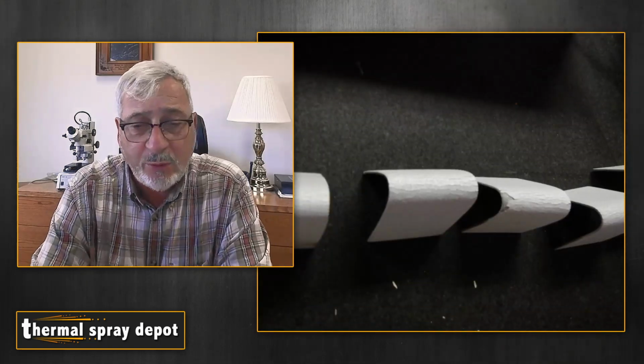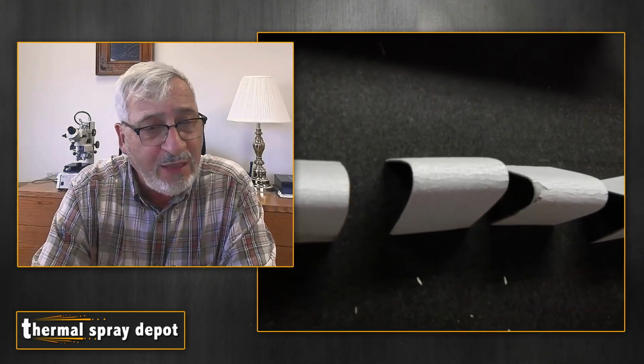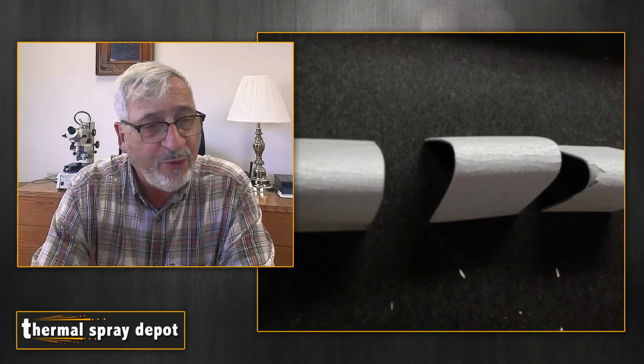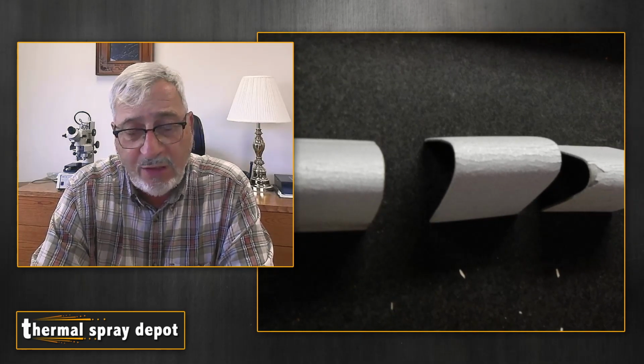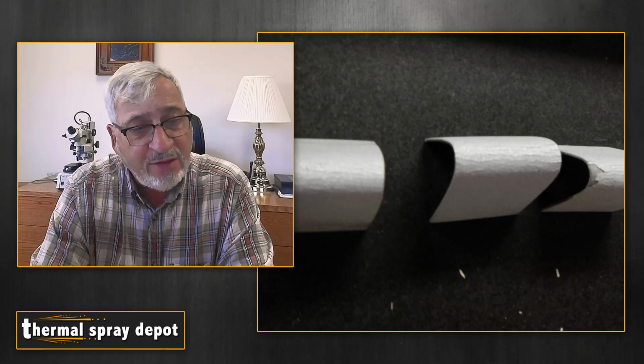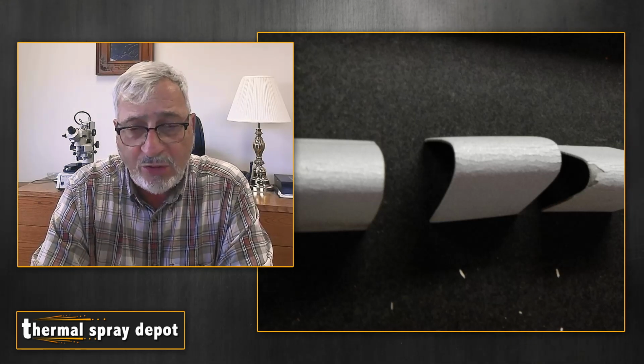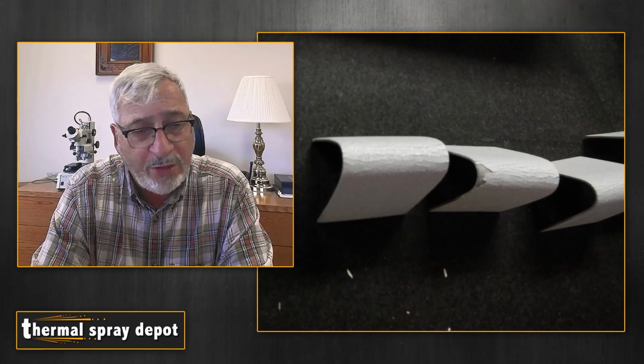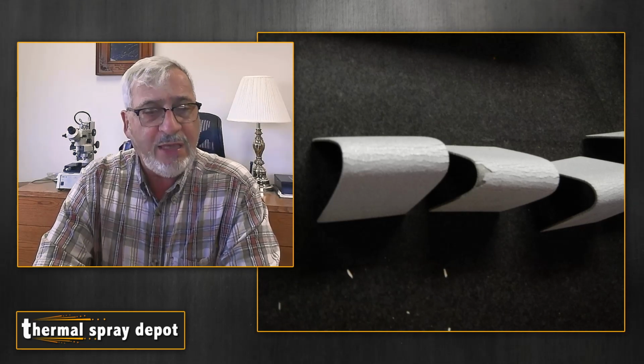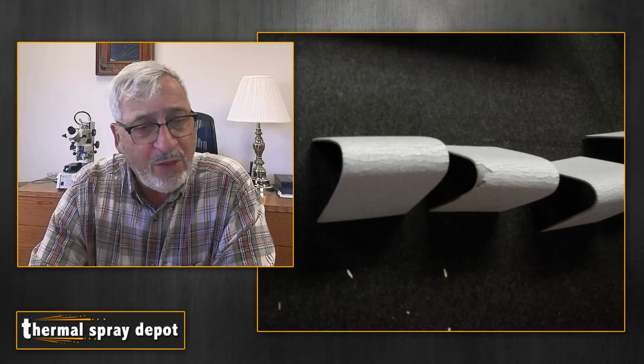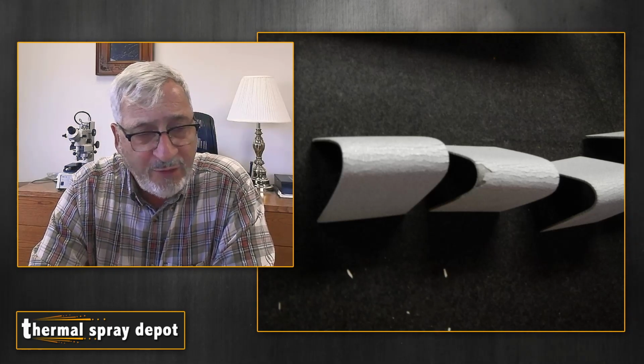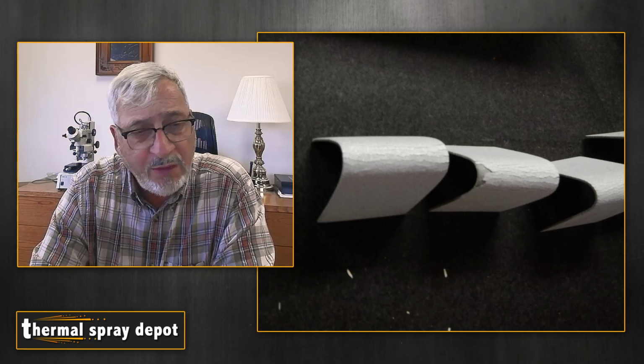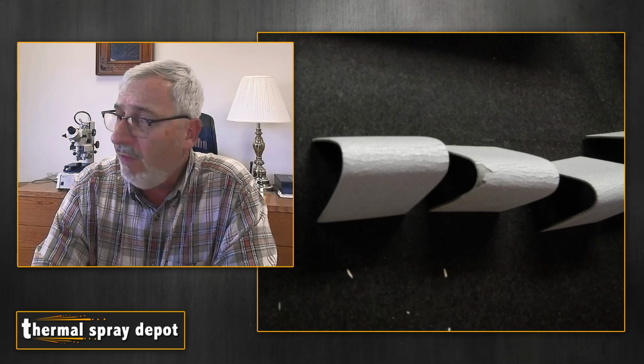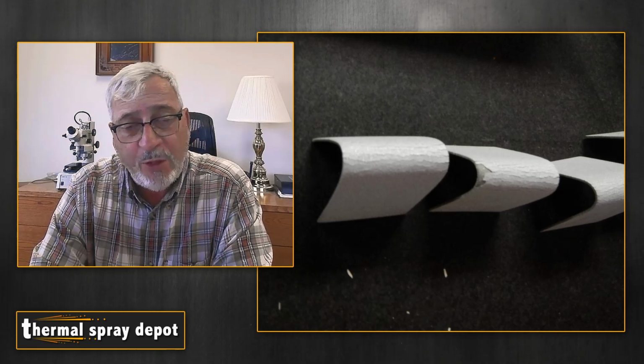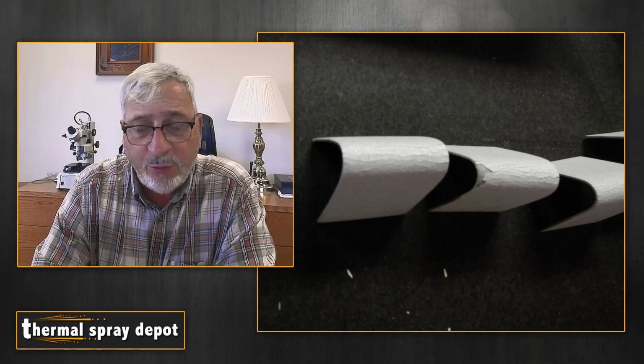This is an example of some really good coatings. You'll see that the radius is much tighter on these. And the first two pictures on the left, that coating is just starting to crack. And that's an extreme, going 180 degrees like that on a sharp bend. Yeah. And the third one from the left, you can see there's some spalling starting to occur. So this is a successful coating that we like quite a bit. And if you dug into that, you'd probably see there was something with that corner right there that caused it to fail. Now, there are specifications on the bend radius.